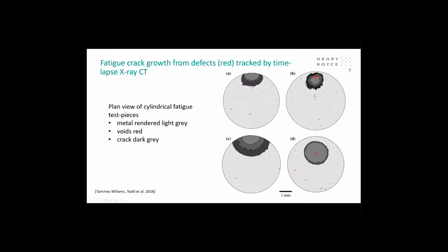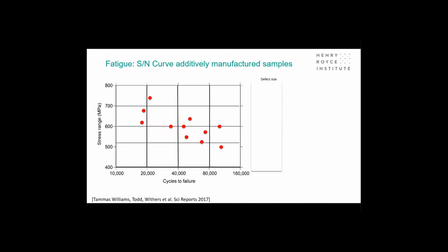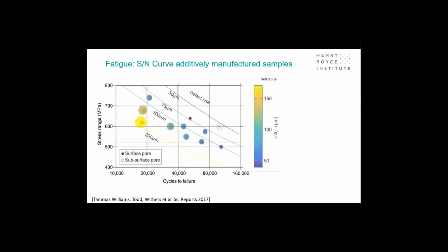And so we can get a good understanding of crack nucleation and growth, and therefore make fracture mechanics predictions on the fatigue life of additively manufactured parts. So if we look at the SN curve that I showed previously, the stress range against cycles to failure, if we are to image those samples, we can identify the critical defects, and you can see that when we replot